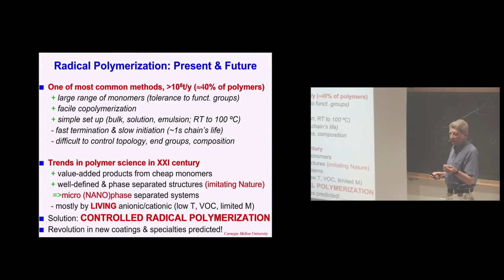What Michael Szwarc did in 1956, he invented this living polymerization and block copolymers. But this has to be done at temperatures of minus 80 degrees, in complete absence of carbon dioxide or air, no moisture, down to really parts per billion removal of the moisture, because otherwise you will quench these reactions. So if you take advantages of this radical polymerization and some advantages of this living anionic or cationic polymerization, you can combine them together, and this was beginning more or less 20 years ago, how the controlled radical polymerization started.